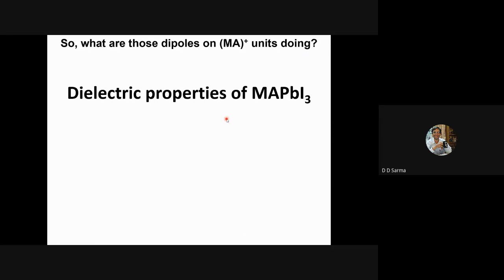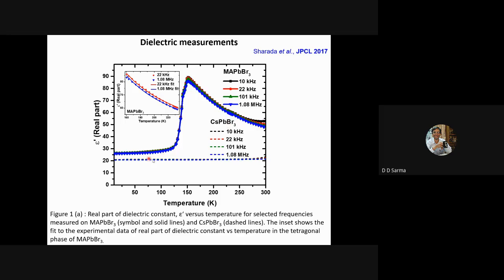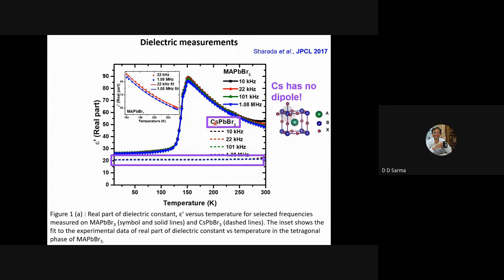statically disordered. In fact, in order to understand that, what we are going to do is look at this spectrum, this particular plot, which is a dielectric plot. I'm plotting dielectric constant here, temperature here, of one of these materials, MAPbBr3, which has a dipole at MA. I can do another thing. I can take out MA and put cesium there. Cesium has no dipole. It's one metal ion. And then I see dielectric constant looks like this. Rest of it is the same, PbBr3. And there is no contribution from the dipole.